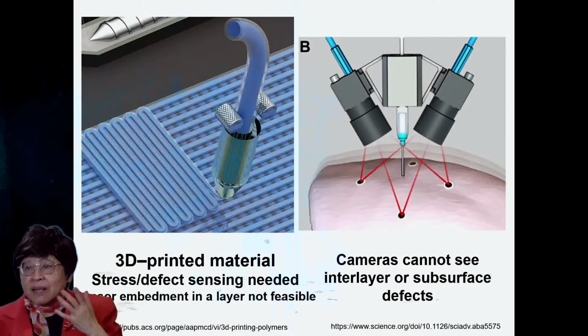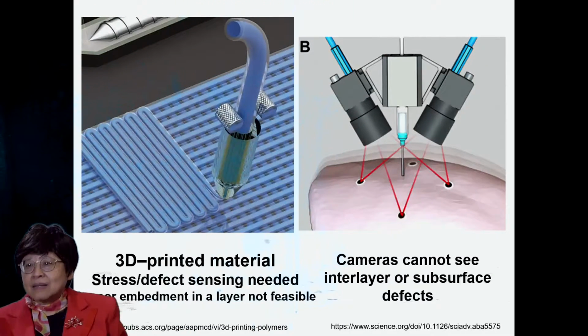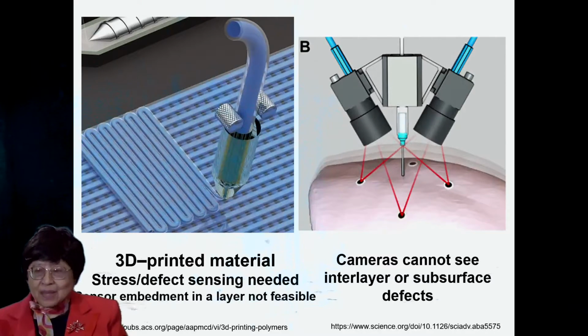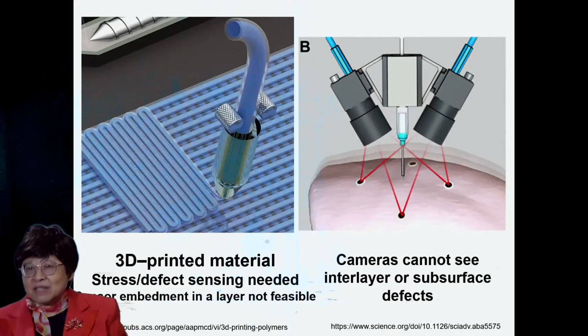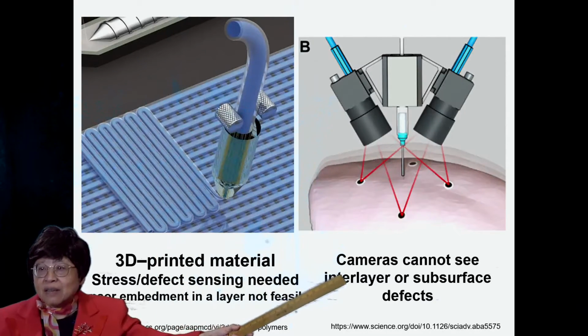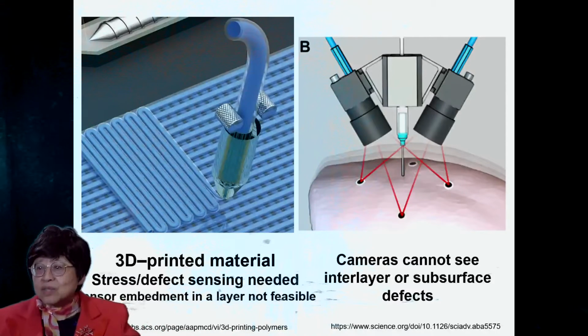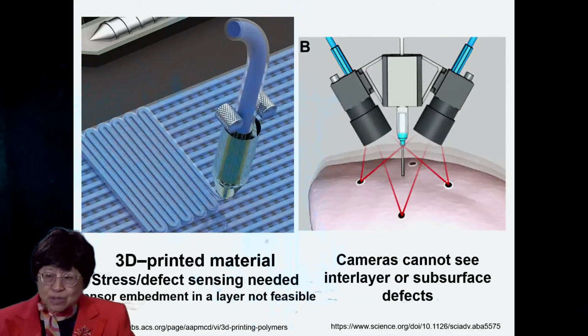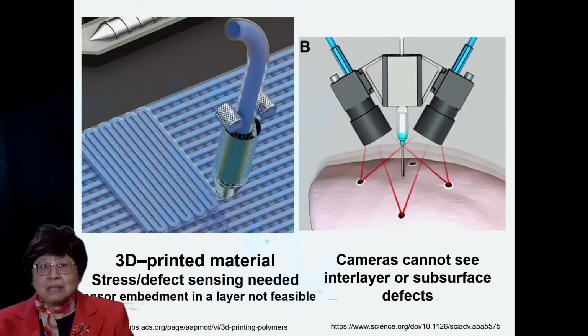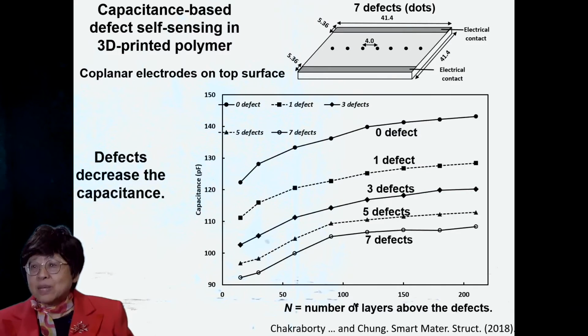Now, 3D printing needs stress or defect sensing very badly because there are defects, particularly those defects that are between the printed layers and subsurface defects. Those cannot be seen by cameras, and cameras are the conventional methods that people use for sensing defects in 3D printed material. But we can use capacitance-based sensing.